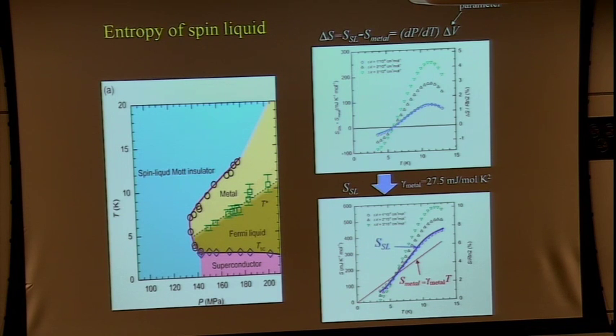This resistivity. Below 3 kelvins, this is superconductivity. So we cannot clearly determine the phase boundary because some sort of percolative superconductivity occurs and affects the behavior of the insulating phase. So we cannot clearly determine it below 3 kelvins. This is an experimental restriction.